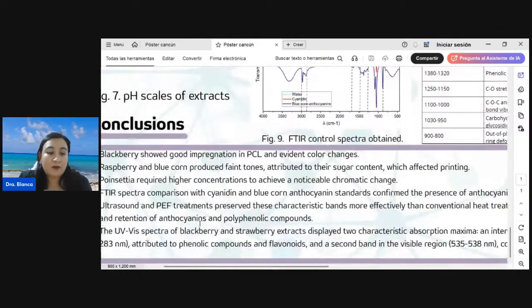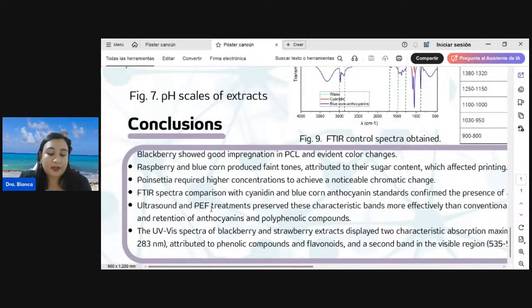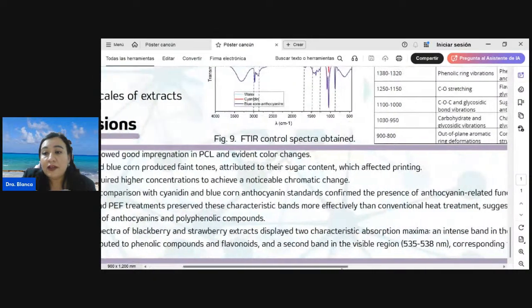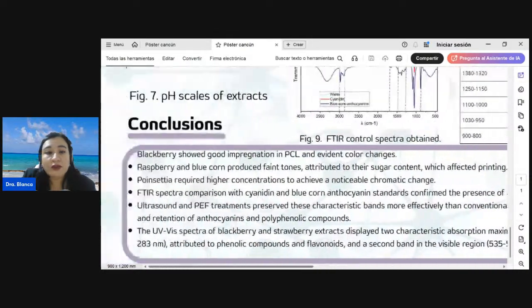Finally, I am ending with the conclusions. Blackberry showed good impregnation in PCL and evident color change. Raspberry and blue corn produce faint tones attributed to their sugar content affecting printing. Poinsettia requires higher concentration to achieve a noticeable chromatic change. FTIR spectra comparison with cyanidin and blue corn anthocyanin standards confirmed the presence of anthocyanin-related functional groups.